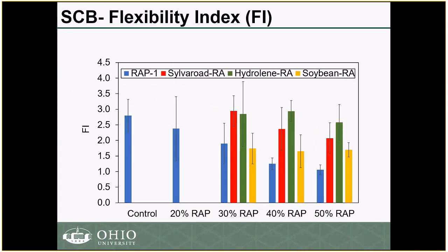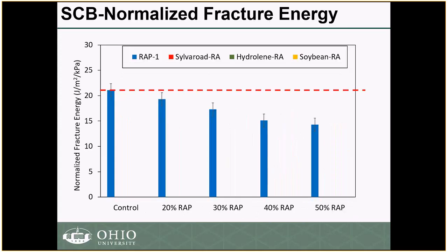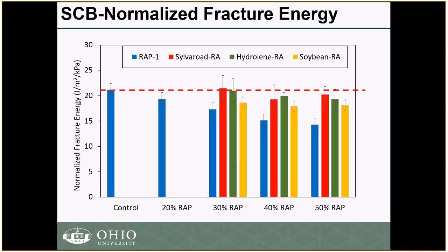Now, very important, before I go to the next slide, is that the variability of the flexibility index was relatively high. It was between 20 and 25%, and this is something that we noted in the previous study, and that's why we use the normalized fracture energy. For the normalized fracture energy, the coefficient of variation was less than 15%, and you can see it has a very similar trend to that of the flexibility index, which we also noticed in our previous study. So this is another parameter showing the same conclusion: if we use a softer binder, fatigue cracking resistance might be maintained.